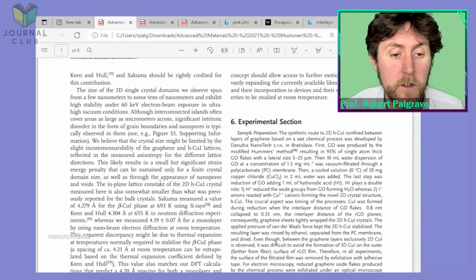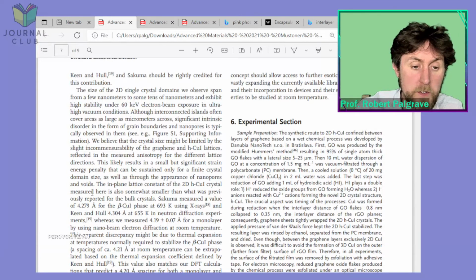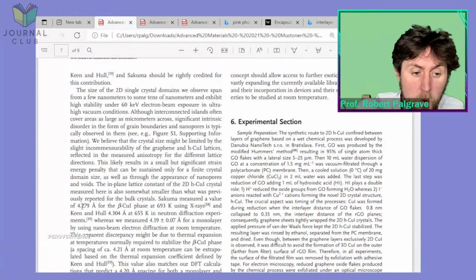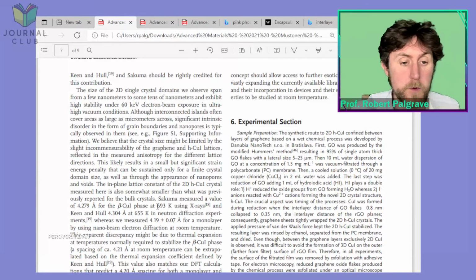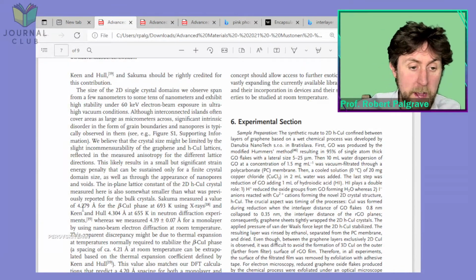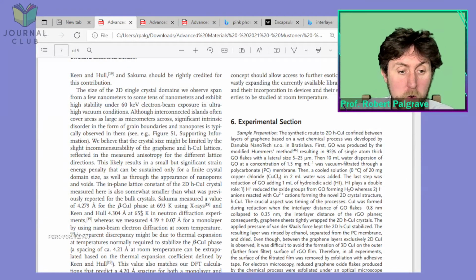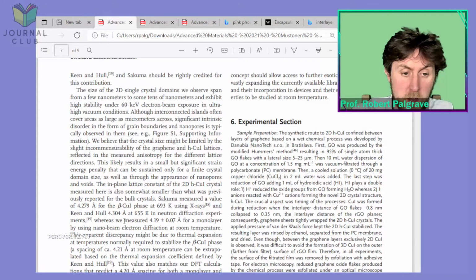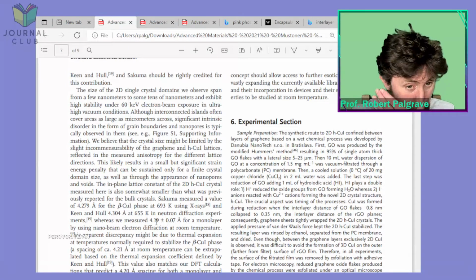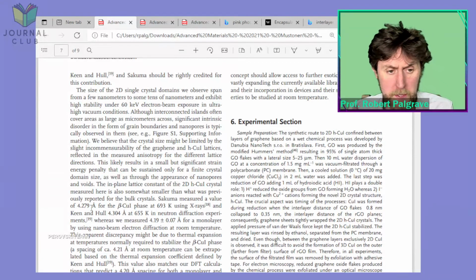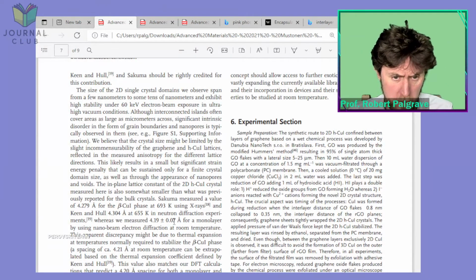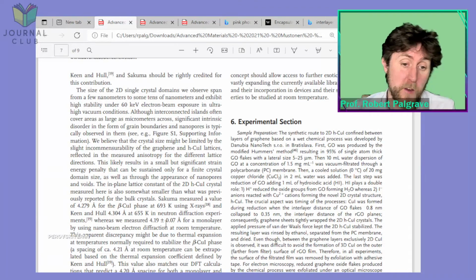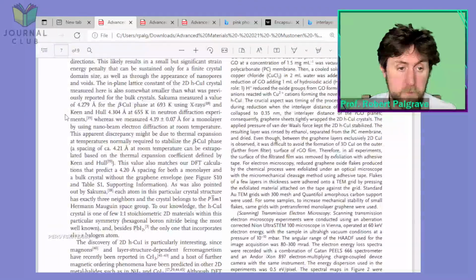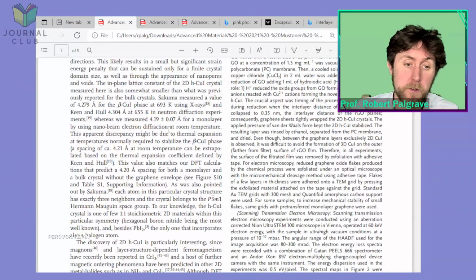The in-plane lattice constant of 2D hexagonal cuprous iodide crystals measured here is also somewhat smaller than was previously reported for the bulk crystals. Sakuma measured a value of 4.279 angstroms for the beta cuprous iodide phase using X-ray diffraction, and Keen and Hull 4.304 at a slightly different temperature using neutron diffraction, whereas we measured 4.19. Okay, that's actually quite a lot smaller, more than 0.1 angstrom smaller. Significant difference, definitely a measurable difference there, for a monolayer using nanobeam electron diffraction at room temperature.